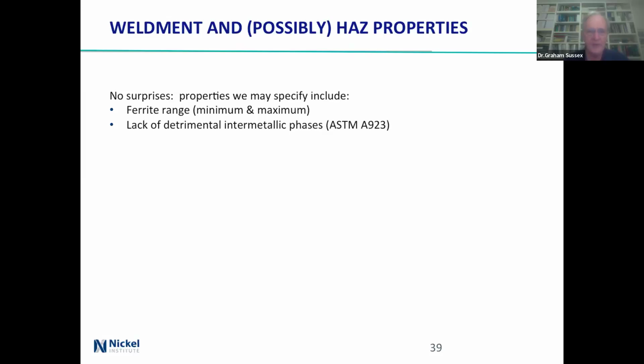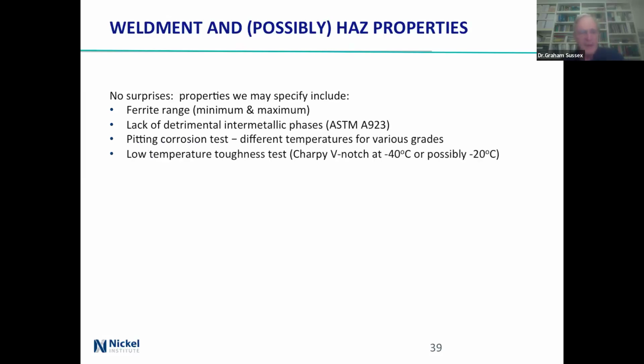Okay, what are the HAZ properties? Well, you can specify things, the ferrite range, maximum and minimum, but how big is the HAZ and how are you measuring it? Intermetallic phases, well, okay, yes, you're just going to have to look at it. A pitting corrosion test, yes, use different temperatures for different grades and they're set out in the standards. And low temperature toughness, V-notch at -40, possibly -20 if you are not going down a long way, but a lot of standards just say -40 and that's it.